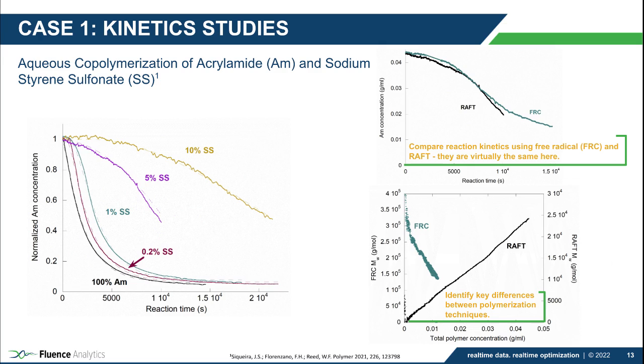The first thing observed, as we can see on the left plot, was that as the initial sodium styrene sulfonate content increases, the slower the conversion of acrylamide gets, which led to the hypothesis that acrylamide is initiated more easily by the initiator, but then prefers to transfer radical to the other monomer instead of polymerizing. And once sodium styrene sulfonate reaches a certain minimum threshold, acrylamide polymerization progresses with normal speed and exponential decay.